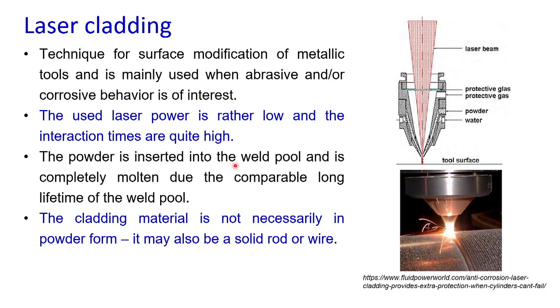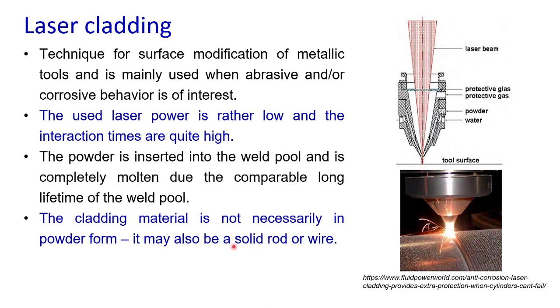The powder is inserted into the melt pool and is completely molten due to the comparably long lifetime of the melt pool. As we are enhancing the interaction time, there would be a long lifetime of the weld pool, and during this process of solidification, we are injecting the cladding material. So we are applying laser power. Laser power is melting the material for a longer duration of time, and during that period only we are applying the cladding material. The cladding material is not necessarily in powder form; we can have the cladding material in solid form, or in the form of wire as well.